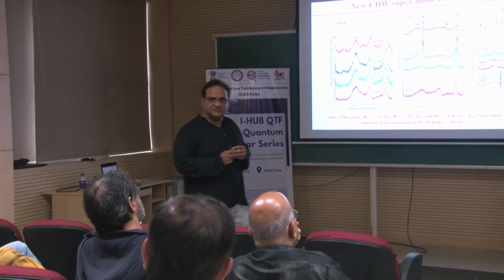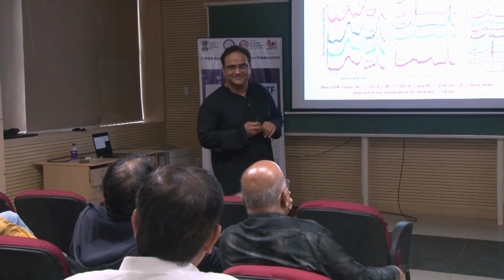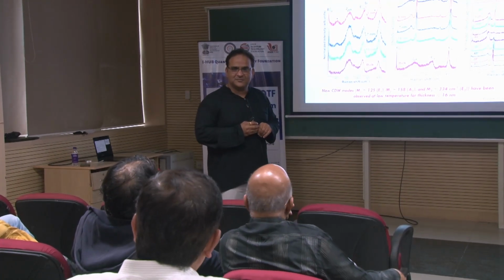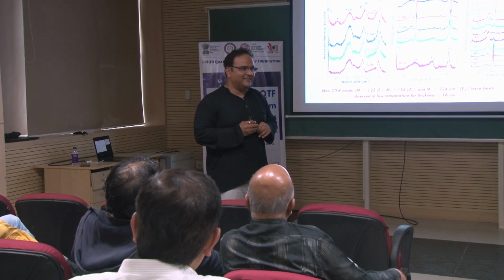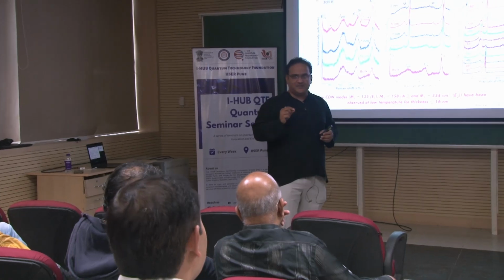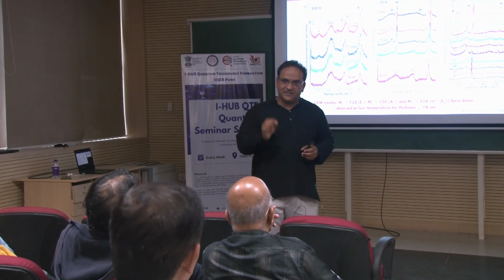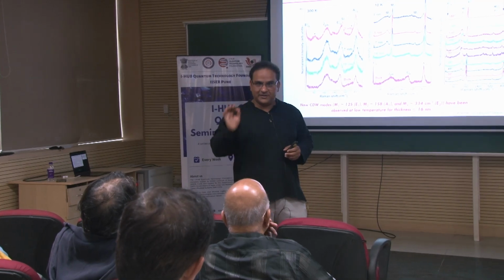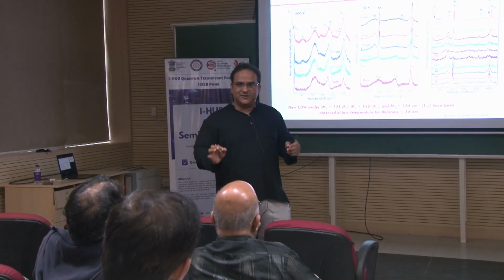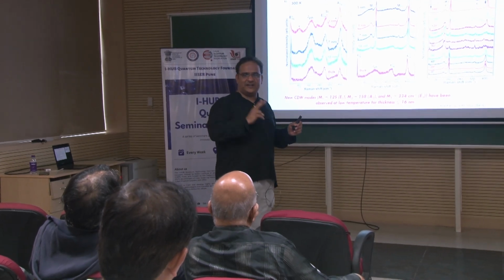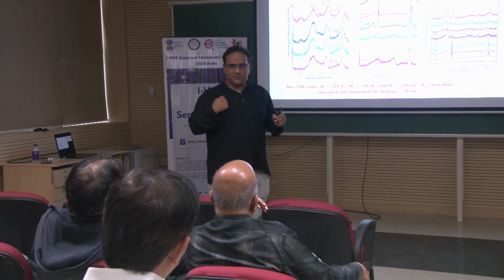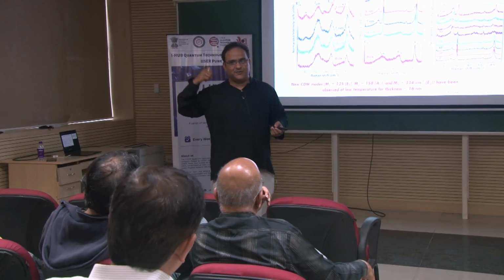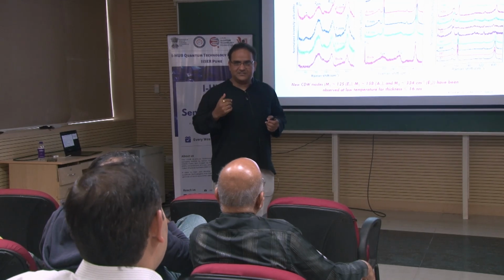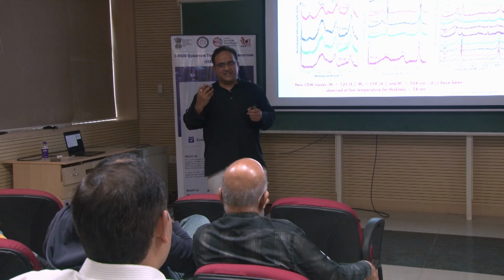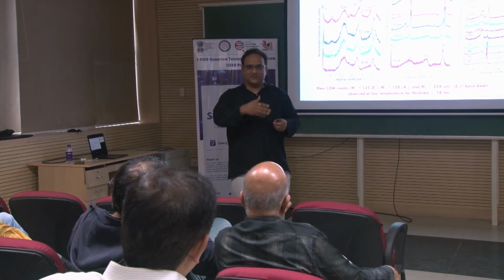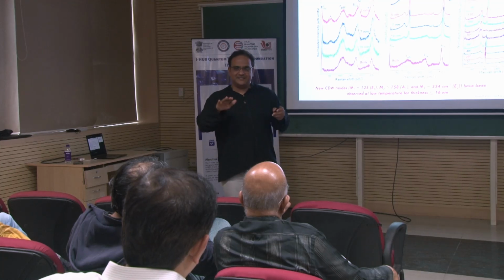When you mentioned that two acoustic phonons come together and give an optical mode, in your Raman signal, how do you know that? Like two phonon or three acoustic phonon? Okay, so an interesting aspect is that there is a paper published in 1970 in Pramana by Bera and Mohanty. They did the theory, and for the first time they mentioned that this two phonon mode can come from the interaction of two acoustic modes. Now, my job is to find out the evidence, because Raman can show it here. We found it, then we went to Umeshda, who was telling us that there may be strain or something, so he has to rule out all the possibilities, and that is what we wanted to do.